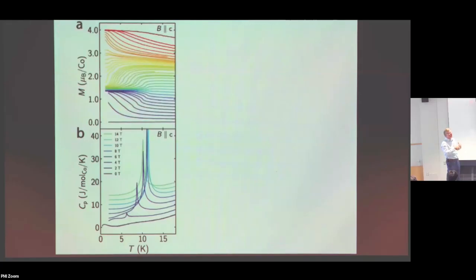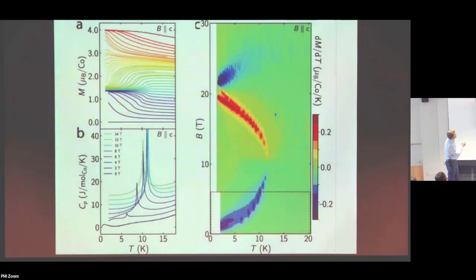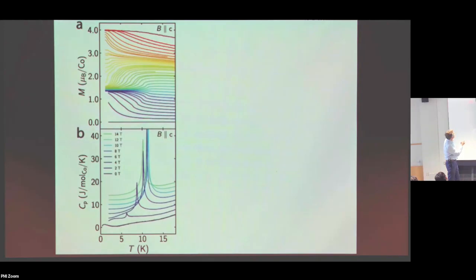Then when we come to higher field, we have to switch to magnetization measurements, because we didn't have access to specific heat at those very high fields. But this is what the data look like. I didn't show my field scale, but this is maybe 25 Tesla, and then we're coming down. And the thing I like about these data is you can see that the system really, really likes the 1/3 magnetization. If I don't give enough field, it'll just pull itself up by its bootstraps and get to that magnetization.